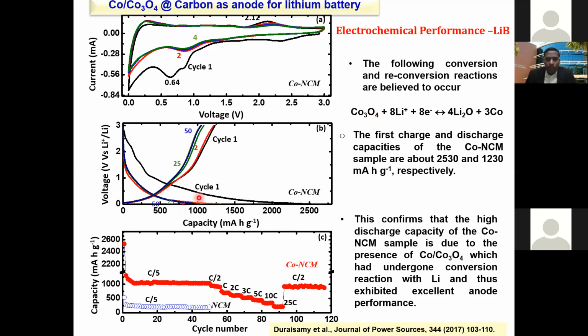Then you quantify how much lithium it can store, or the capacity it can store, or energy density. If you multiply the capacity and voltage, you can see that in your first cycle, you can get as high as 2000 plus milliampere hour per gram capacity, which stabilizes at 1000. And very characteristic of a battery is to operate at a different C rate. You can see that the present material can be operated at a different C rate. A capacity as high as 1000 mAh can be obtained using cobalt oxide carbon as an anode material.